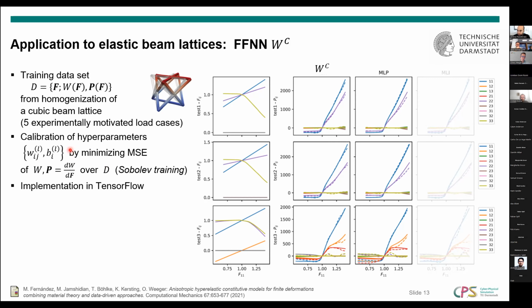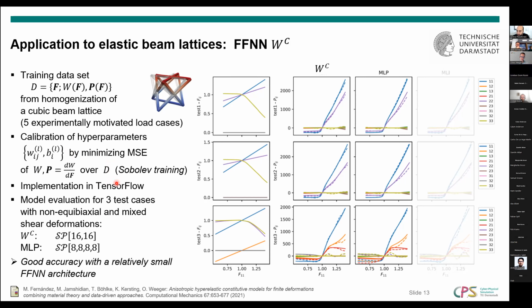So we find the hyperparameters of the neural network by implementing all of this in TensorFlow and training it to certain data, like I showed earlier, where we include uniaxial tension, biaxial tension, and so on in the training cases. And then we generated some test cases which combine all sorts of deformations. For instance, in this bottom case over here, you have a combination of tension and shear behavior. And what you see over here is basically the results of the stress strain curves that we get from the trained model here with only 2 hidden layers with 16 nodes each, where basically we see a very good agreement of the continuous lines, which are the data, and the dashed lines, which are the model predictions. So with relatively small architectures, we get here a good accuracy in predicting the stress-strain relationship.